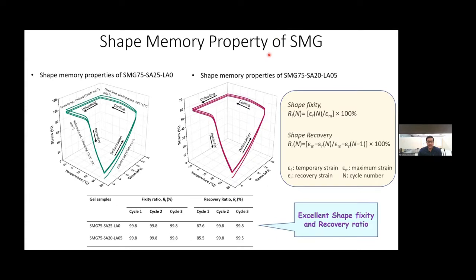Here is the dynamic mechanical analysis data of this material. And we have found that both compositions have an excellent shape fixity and recovery ratio. And you can see here for all cycles, the shape fixity ratio is above 99% for all the layers, and the recovery ratio for the first cycle is above 85%, and from cycle 2, the recovery ratio is above 99%. This difference, we call it the training phenomenon here.